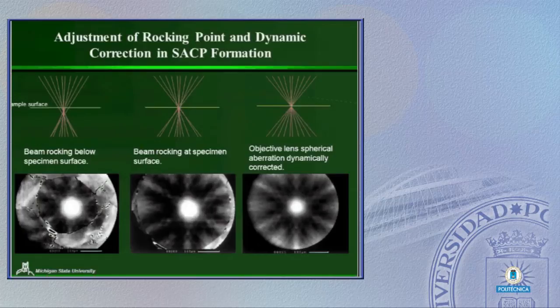But if you actually adjust the strength of the objective lens as you rock the beam, you can get that area down much smaller by using a dynamic correction. And as a result, we can get information from a smaller area on the sample. And the smaller the area, the more useful it is for us, because it allows us to measure specific orientations in small grains, or if grains have orientation gradients in them, we can separate those out.